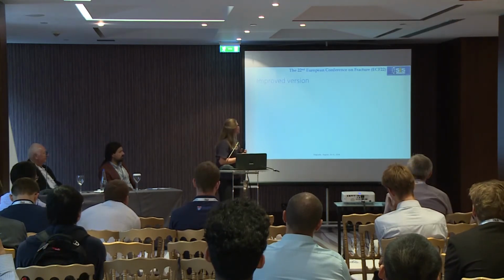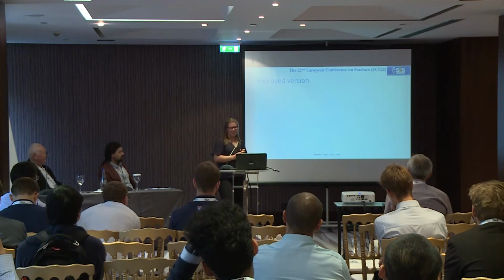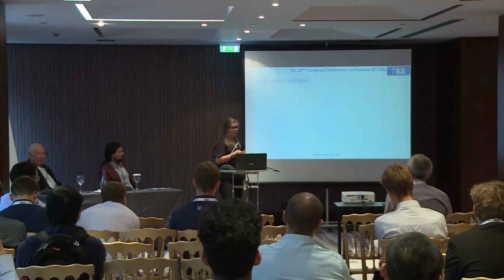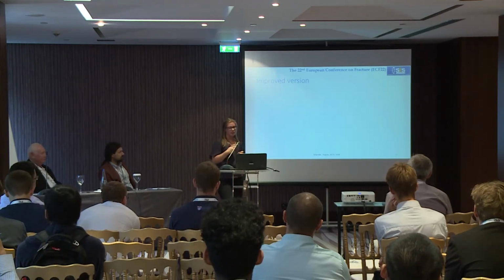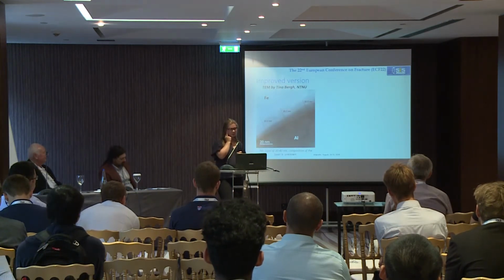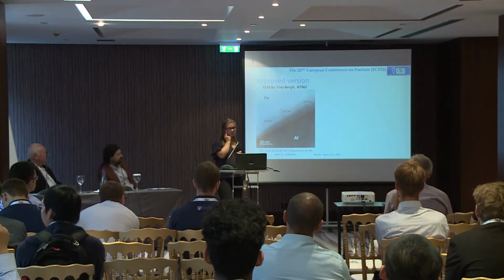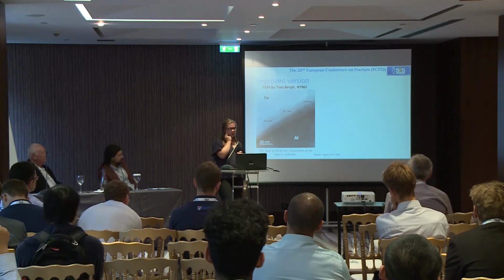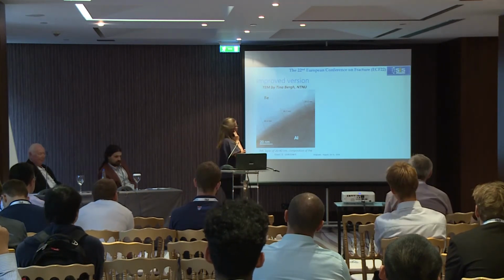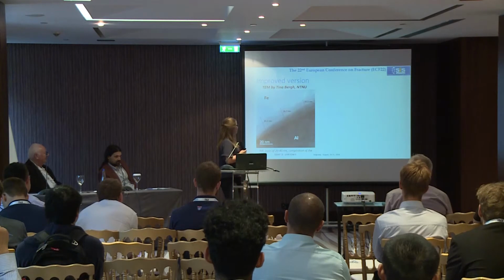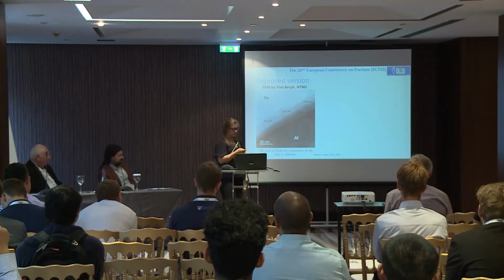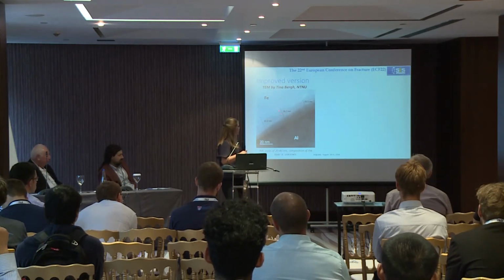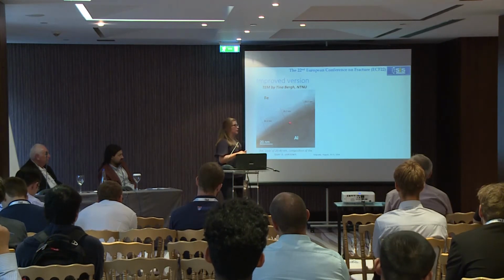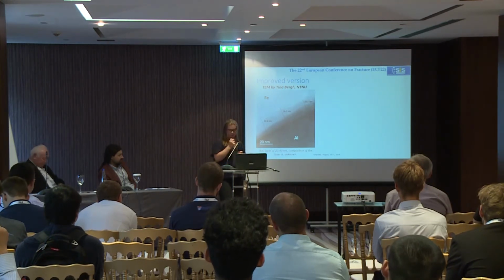Yeah, in fact, there has been an improved version of this joint, and another PhD student at NTNU has been able to detect this intermetallic layer. Her name is Tina Bergh, and she made this STEM image, and she found the intermetallic layer, and it is of a thickness of 20 to 40 nanometers.